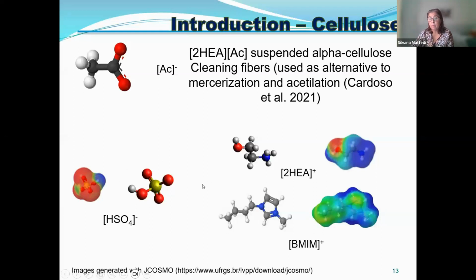But in this work, we are more interested in obtaining the nanofibrils of cellulose. Normally, the work is done with sulfuric acid. So what we used was the hydrogen sulfate anion with two different cations. We use 2-hydroxyethylammonium, and also we use aprotic ionic liquids, that is 1-butyl-3-methylimidazolium, which has this structure.